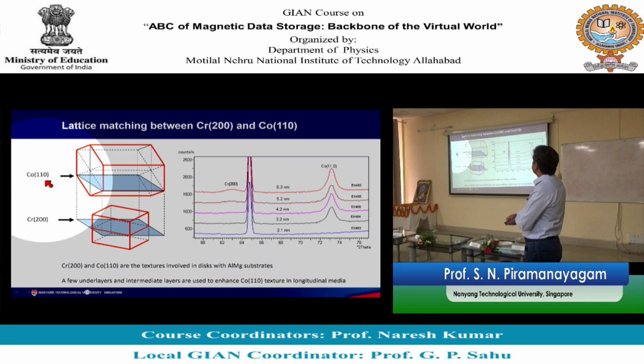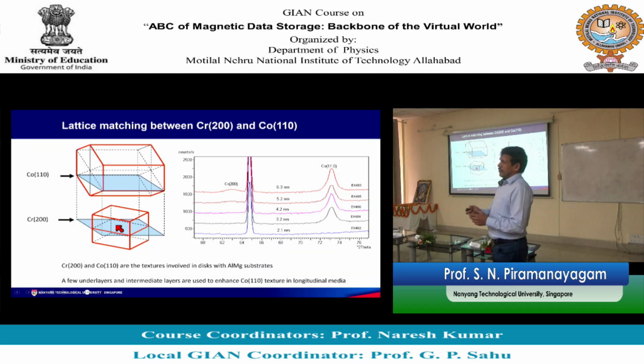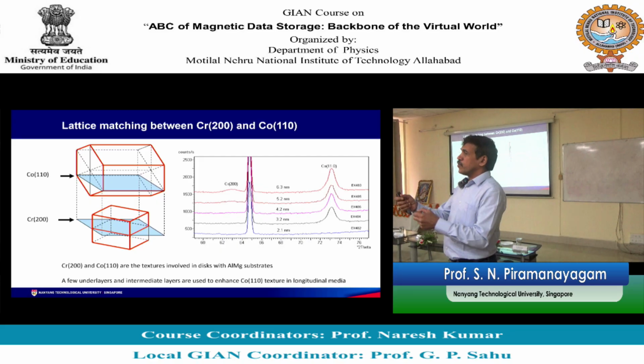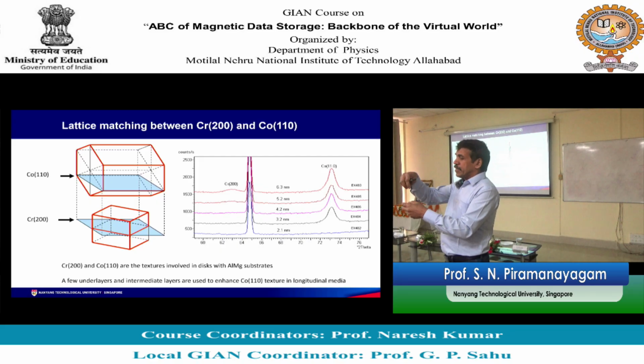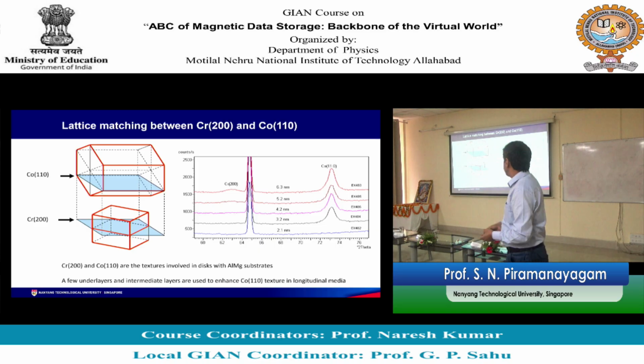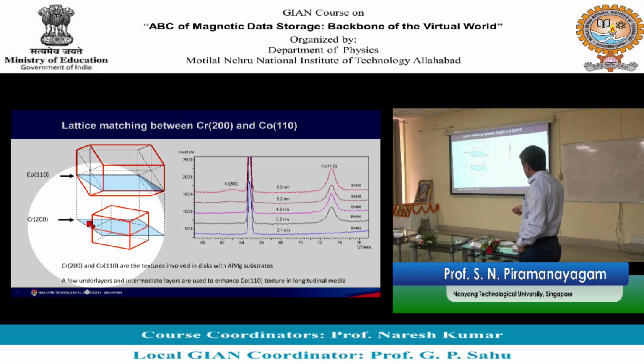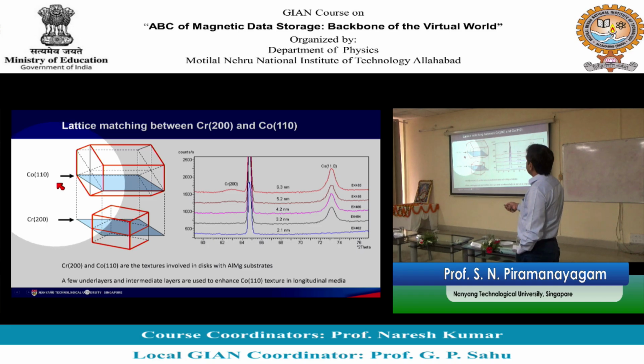Okay. So, now after depositing chromium 200, if you deposit cobalt 110, this atom will be matched to this atom, and so on. It is like Lego blocks, right? You have two Lego blocks of the same size, you can plug one Lego block onto the other block, right? So, in a similar sense, we play Lego with the atoms. Once you grow chromium with a 200 texture, we can grow the cobalt 110 plane.